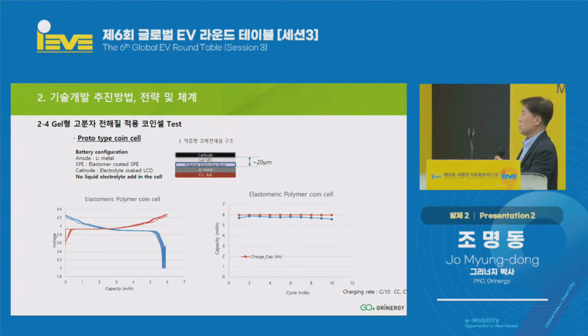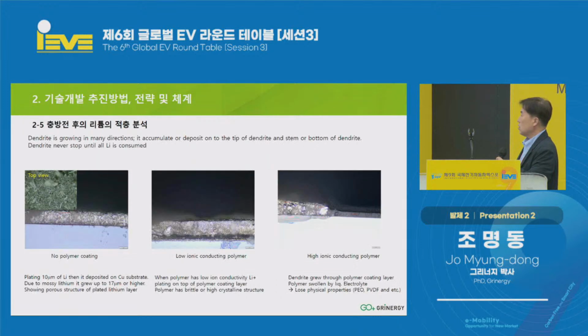So with lithium metal reactivity, we don't see anything. So we've done testing. What you are looking at right now is the lamination analysis of lithium after charging and discharging. On the top is a copper plate, and anode or lithium material was plated, and right here there was no polymer coating, so we tried to find out how well the lithium grows and how the dendrite is formed. About 10 to 17 micron was what we expected. And you can see that the plating is about 10 micron of lithium deposited on the substrate, and due to the mossy lithium, it grew up to 17 or higher, showing a porous structure of the plated lithium layer.